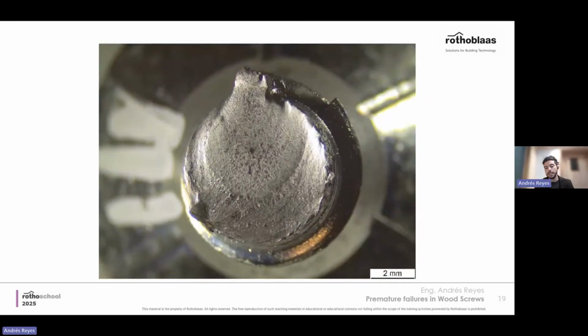What does that look like? What we see here is a screw that was broken by torsion. So it's like a dry test with immediate torsion, just turning the screw around, and you see here this type of smooth curve. So you see the pattern here, and it very much talks about a torsion breakage. There's also the presence of this, I'm translating from Italian, but it's like a tongue, a sort of reduction and elongation in one of the sides of the section that is very typical of ductile breakages. When you have a hydrogen-induced breakage, it would look more like this.